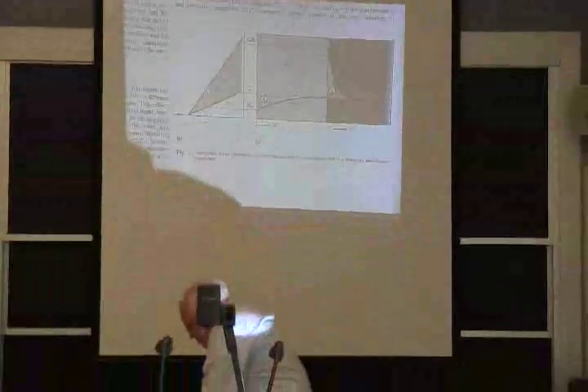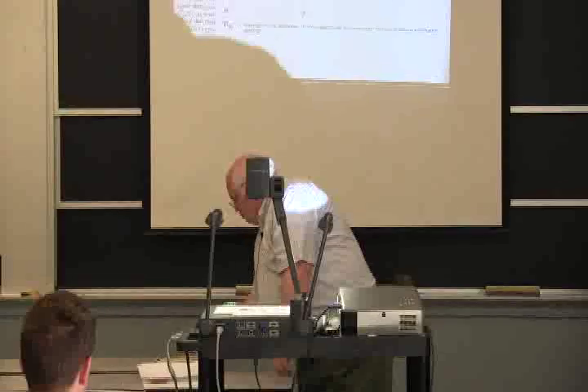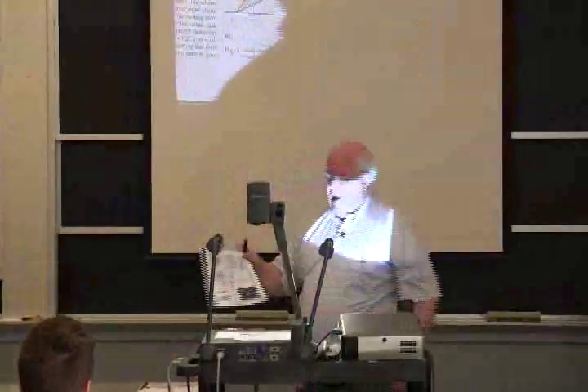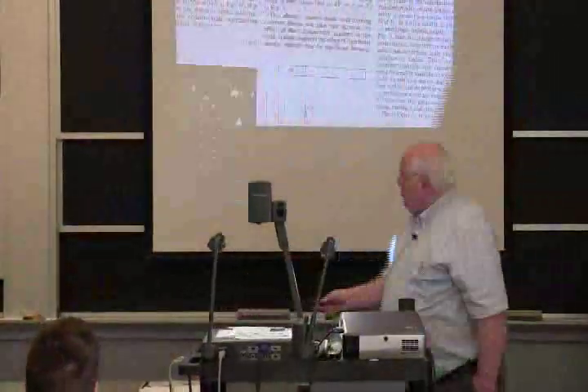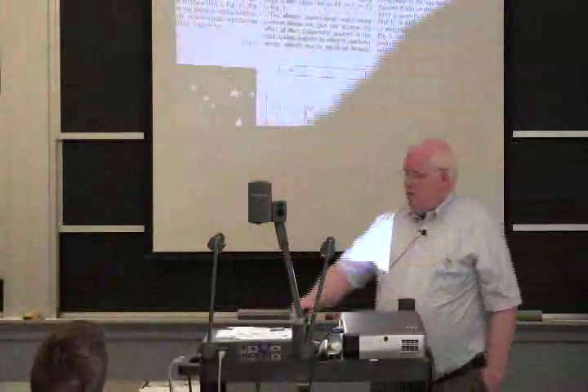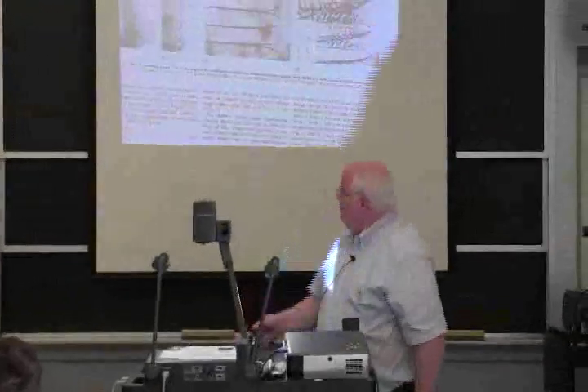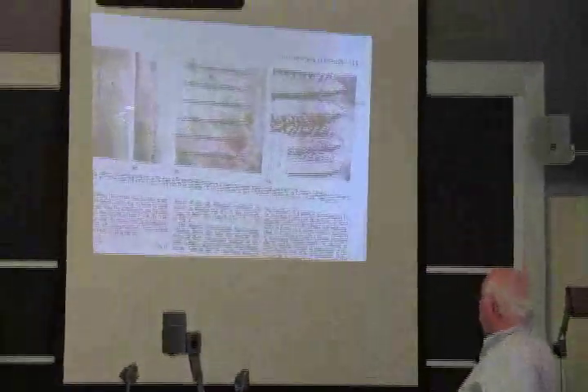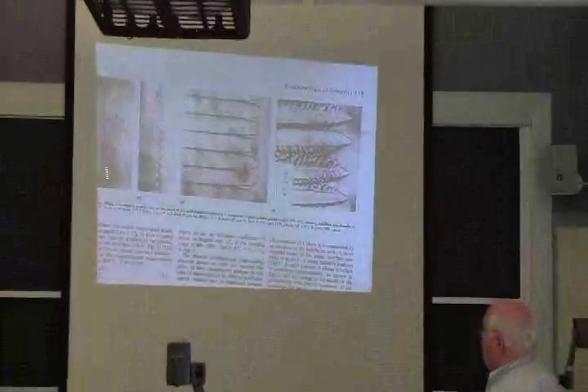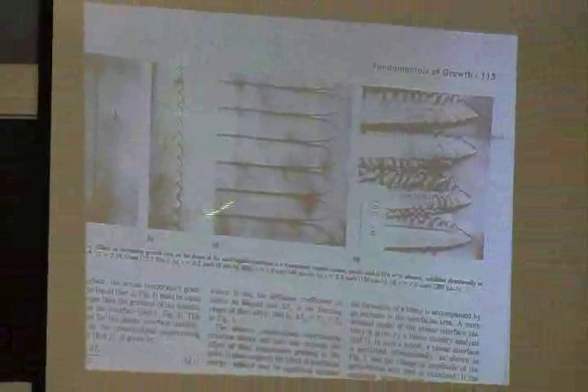That's exactly what causes these dendrites, or the cells we've talked about, in case you wonder why we have cellular growth, or dendritic growth. Here's cellular growth. If you have a very steep temperature gradient, you can suppress this instability. Here's a little instability, here's a big fully cellular growth.